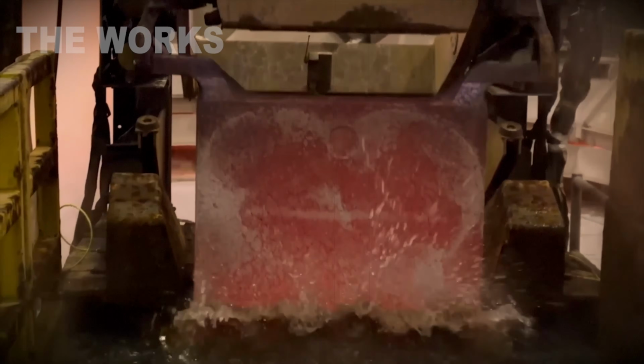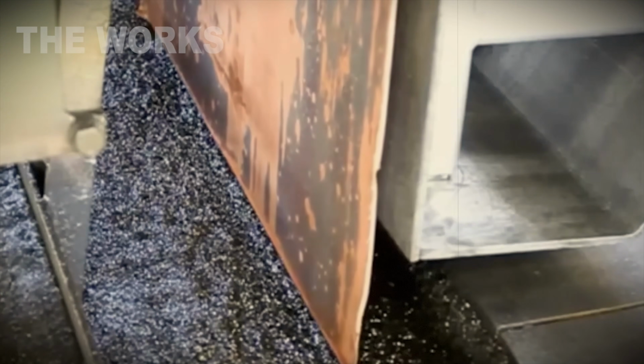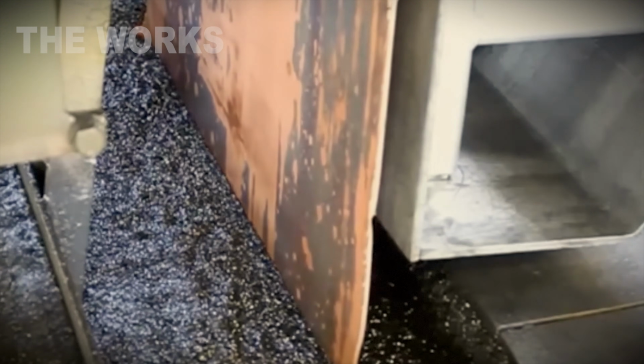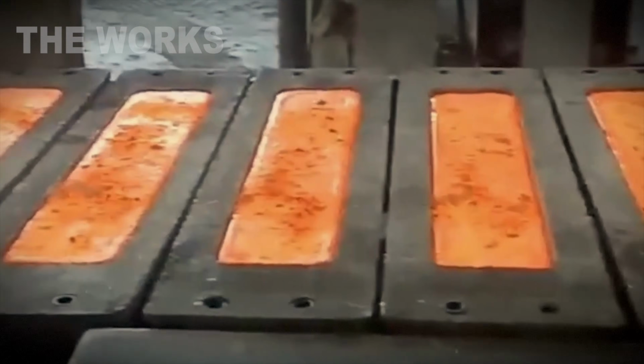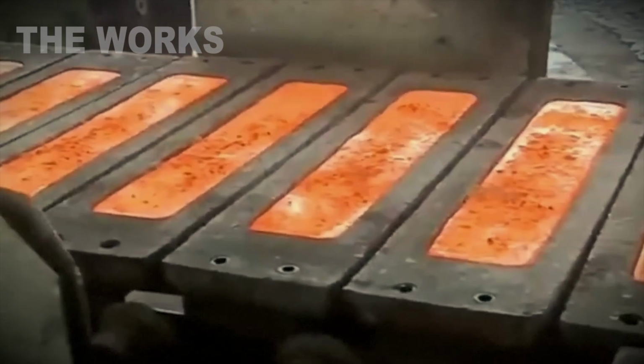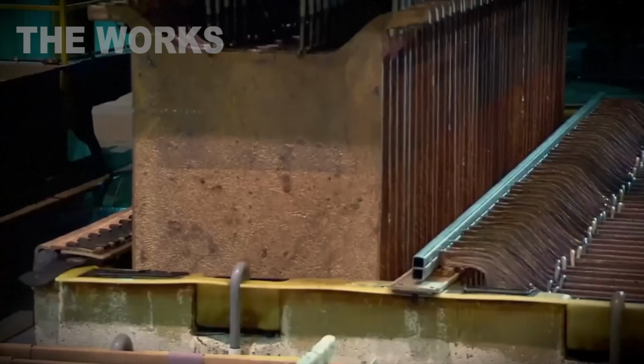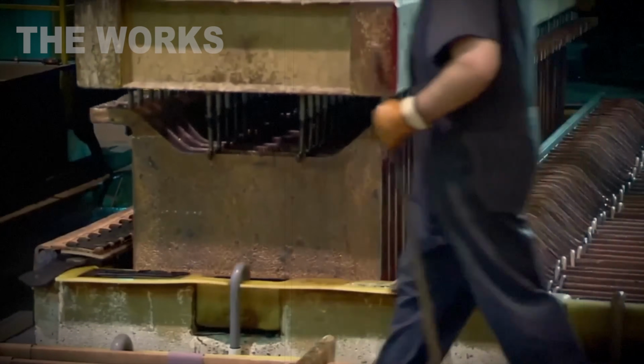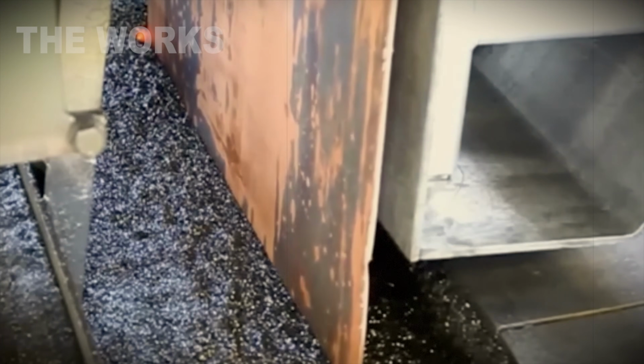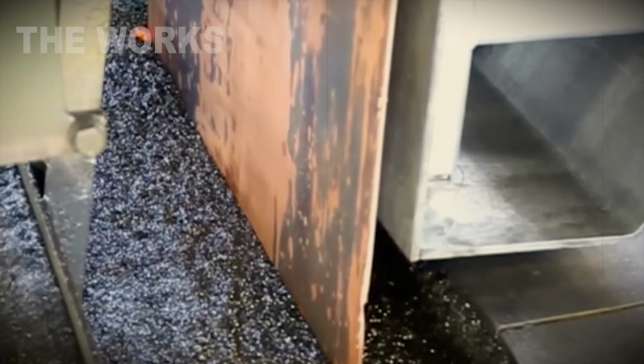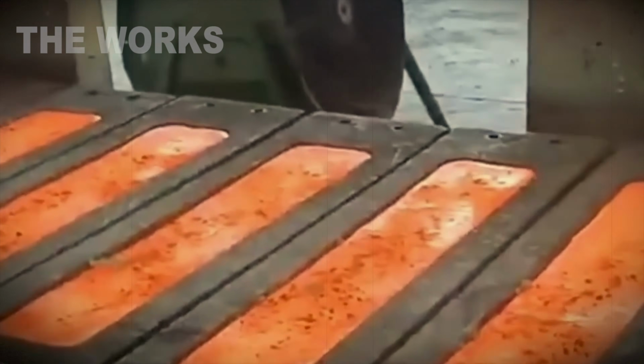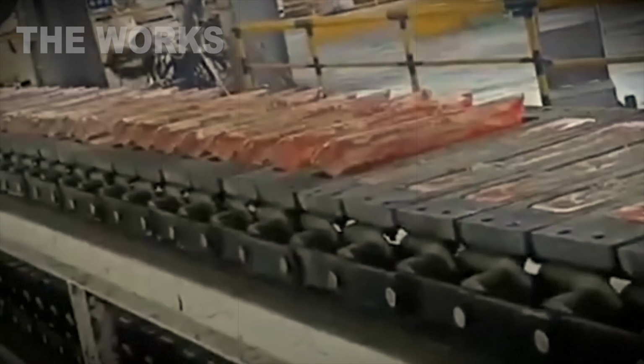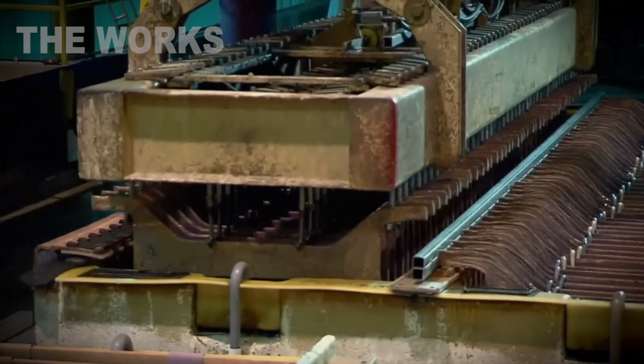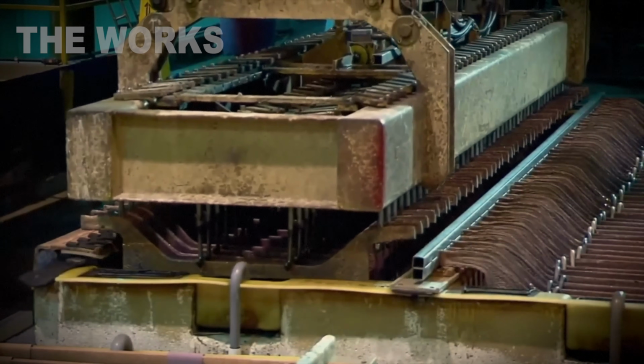The blister copper gets cast into anodes, plates 3 feet wide, 3 feet tall, 2 inches thick, weighing 660 pounds each. They're hauled to the Electrolytic refining shop. Here, tanks 20 feet long, filled with a solution of copper sulfate and sulfuric acid. Into each tank they hang alternating anodes and thin stainless steel starter sheets. A direct current runs through the solution, about 60 amps per square foot.